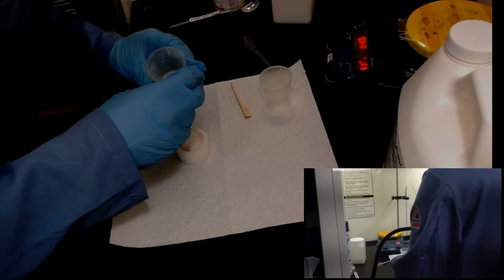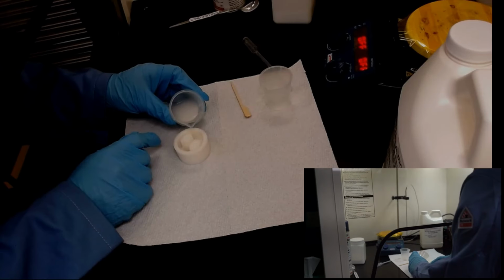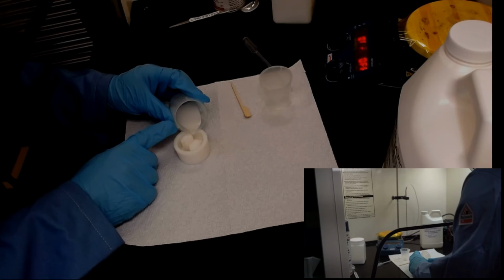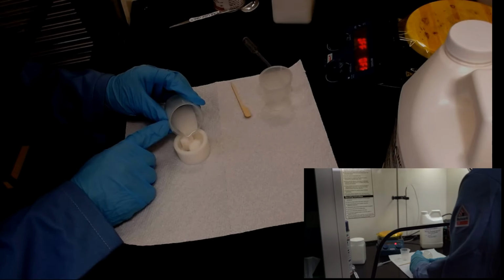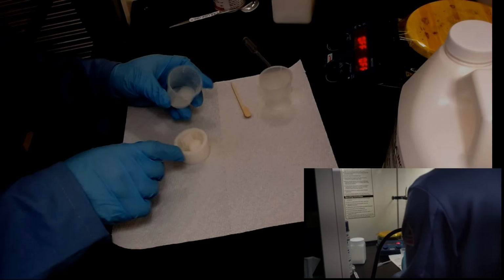This resin does cure in only a couple of minutes, and so it doesn't have as much time to degas as something like a low viscosity epoxy. And while you can do it in a vacuum chamber, it cures fast enough that I don't recommend it.